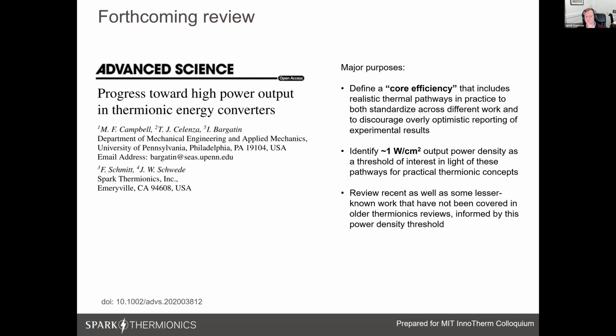And based on those thermal pathways, we identify a rough threshold of on the order of 1 watt per square centimeter as a region of interest. If you can get above 1 watt per square centimeter, we think that this is practical. But if your concept will struggle to get to that level, it's really difficult to justify integrating that into a practical, final, encapsulated thermionic converter. And the final area that we wanted to do is that we feel that a lot of the thermionic literature is just not as well known.